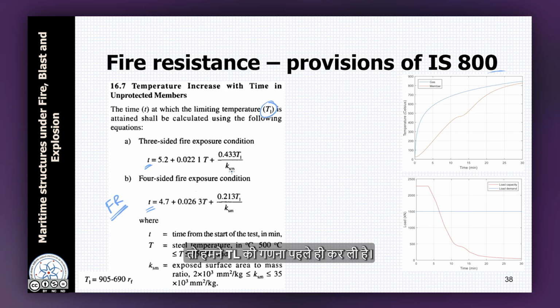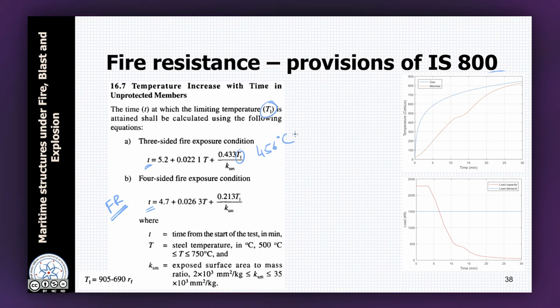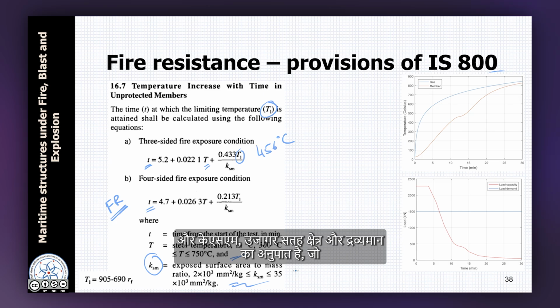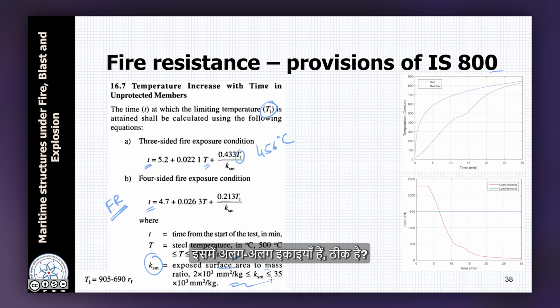So we have already calculated TL, which was 456 degrees Celsius, and T is the actual steel temperature, and KSM is this exposed surface area to mass ratio, very similar to the section factor but somewhat different, it has different units. So using all of that one can calculate the fire resistance as per IS 800, and as we have seen this limiting temperature was somewhere here and the actual rating was somewhere here.